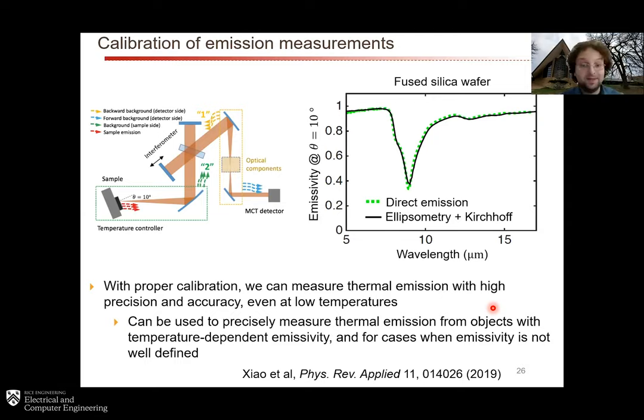So, that long story summarized: after you properly calibrate your instrument and properly do your data analysis, we can now measure thermal emission, and in particular the emissivity of objects, with very, very high precision and very high accuracy, even down to low temperatures. And as you'll see, even with non-equilibrium thermal emitters and other more complicated scenarios.